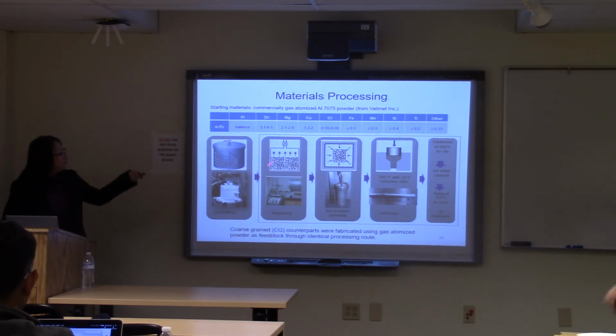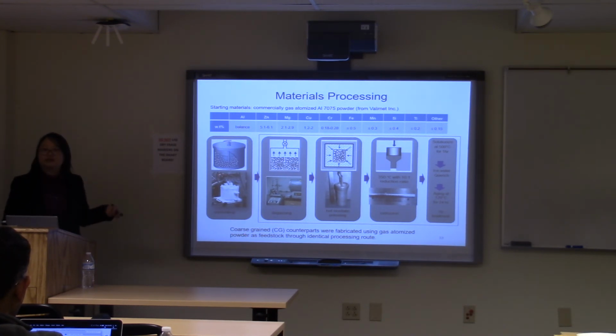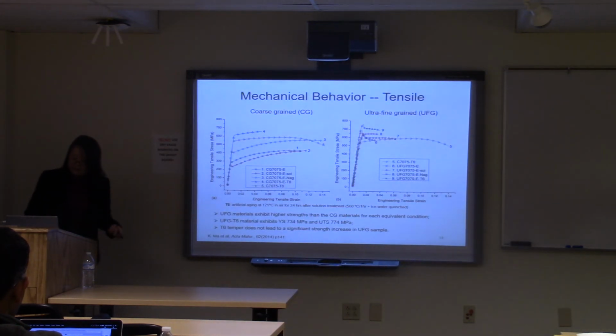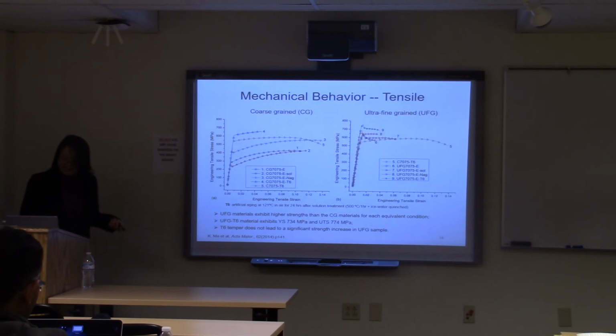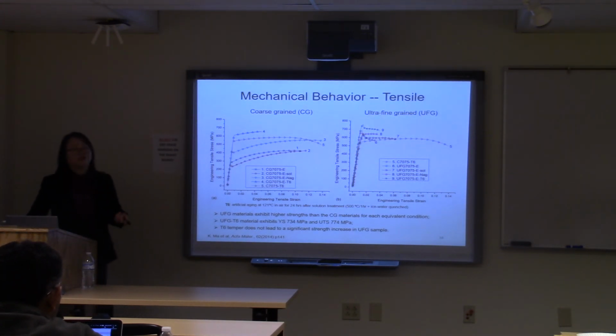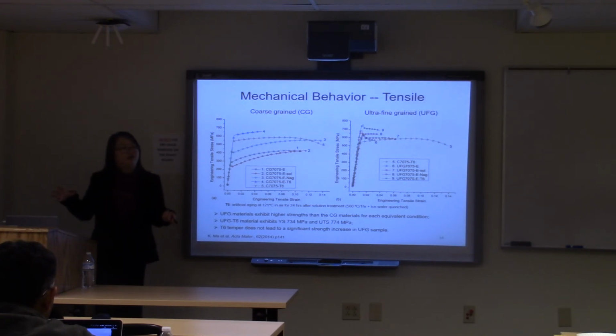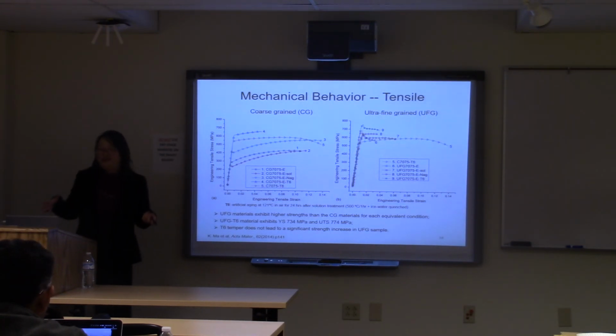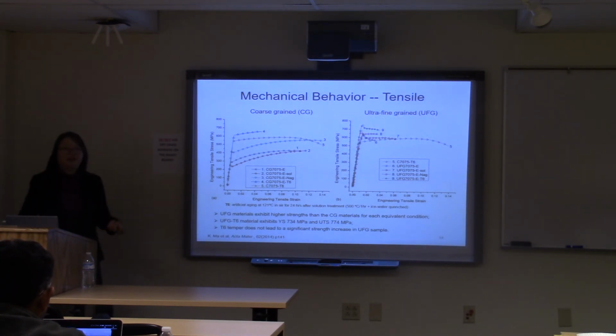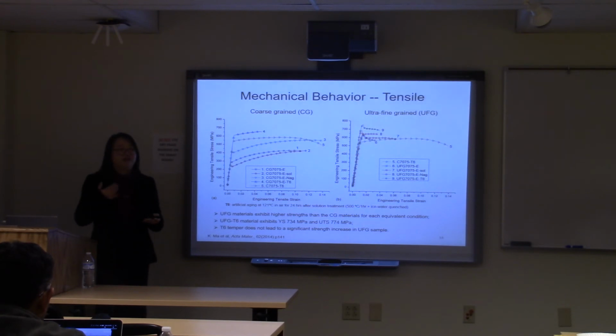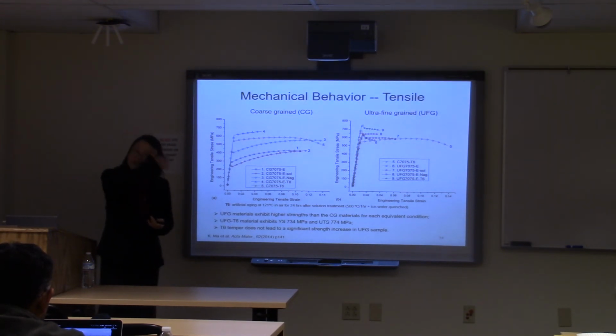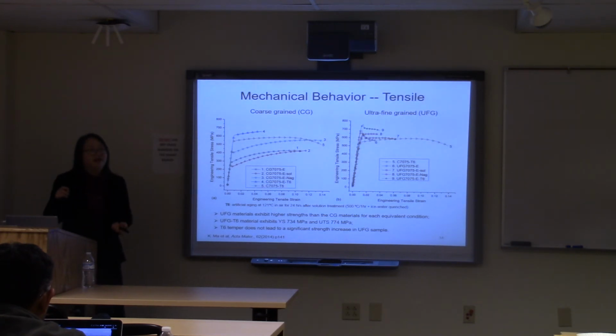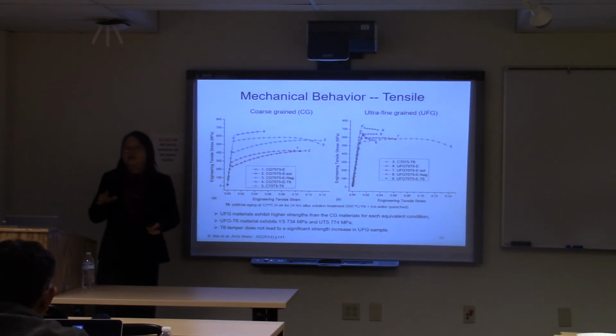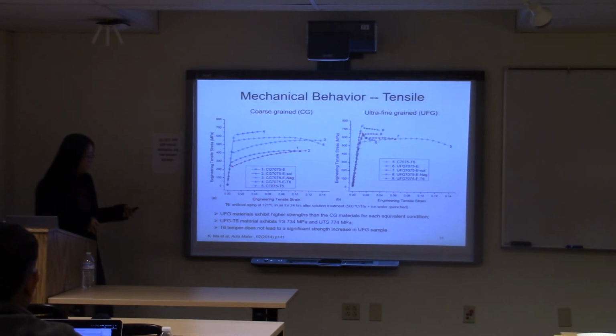But again, for each material, I made coarse grain counterparts using identical processing without the cryogenic milling. So this is what we get in terms of mechanical behavior. On the left, what I call coarse grained is still on the order of 2 or 3 microns because we are still using powder metallurgy. And on the right-hand side, I call it ultrafine grain because after all that thermal exposure during the consolidation and then the secondary thermomechanical process, you get a little bit of grain growth. So now we are not talking about grains on the order of 20 or 30 nanometers. We are talking about 100 nanometers to 200 nanometers here.